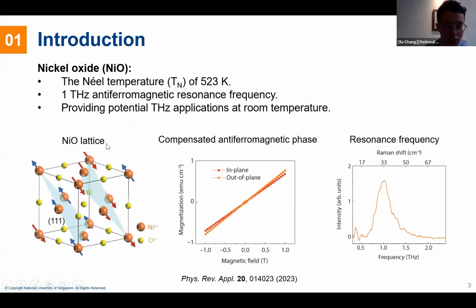So we can see the nickel oxide lattice; the 111 direction is from this plane. This in-plane shows a ferromagnetic coupling, so all the spins are aligned to one direction, and the coupling between these planes is antiferromagnetic. Our result is based on 111-direction nickel oxide, so the surface of our device is deposited on this 111 plane. Our injected current is parallel to the spin alignment. And for our terahertz transmission, this is actually a bulk effect.